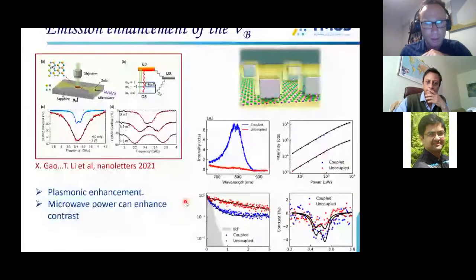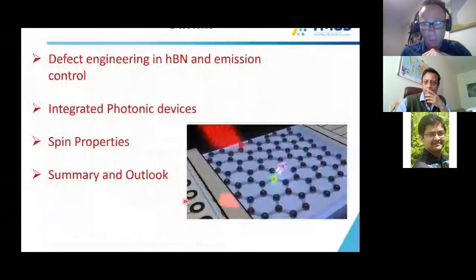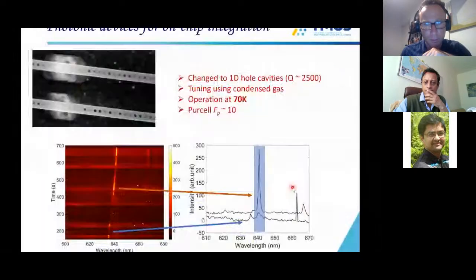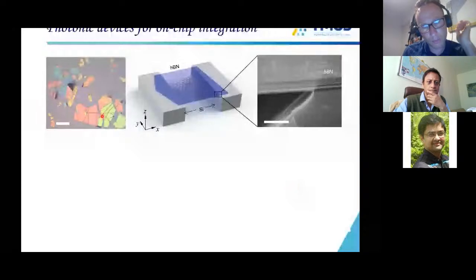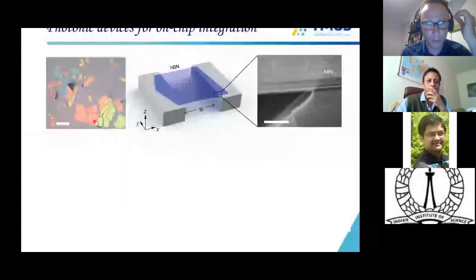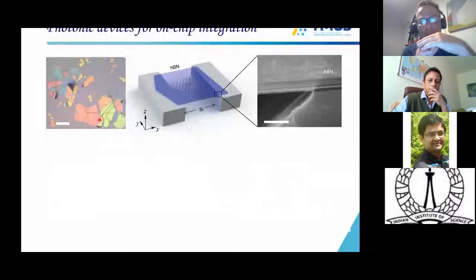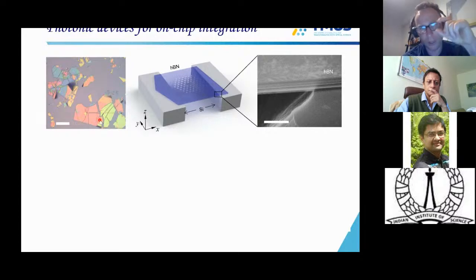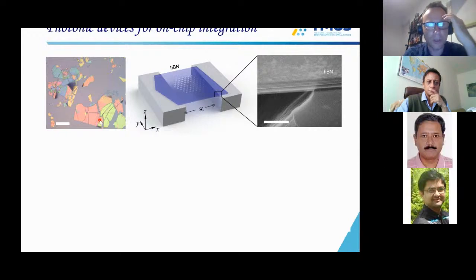So maybe the best slide to explain it is actually this. You see that when we work with hBN, the material is not perfect. We have a lot of grain boundaries, a lot of impurities within the hBN, and when we transfer, there's a lot of polymer residue and a lot of defects. What we think is happening, because it's still an atomically thin layer, is that we basically ionize some other defects, and then there is a charge transfer to the hBN defect, and then they turn on and off. So all this blinking is basically from surrounding defects within the hBN. We haven't really tried to work with large ultra-pure crystals, which are available if you want them. I think that will probably be helpful in the future, but it's from these impurities within the hBN.